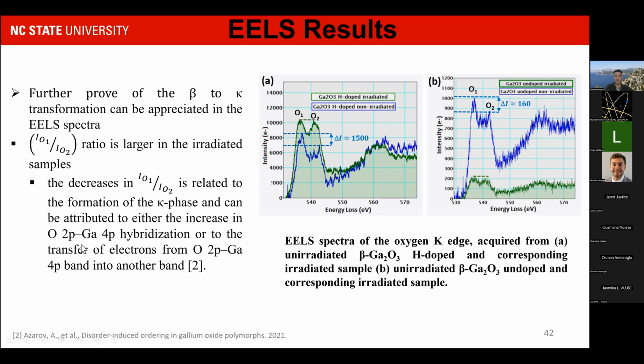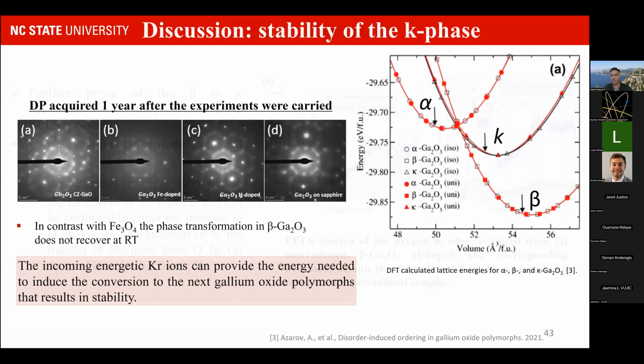It can be attributed to either the increase of the O2, the oxygen that have a specific position in the monoclinic structure, or to the transfer of electrons from O2 to the 4p band into another band. So we observed this type of information consistently throughout, regardless of the sample and regardless of whether it's doped or not. Interestingly, the stability is not just under irradiation by further irradiating, but also over time. So I had my student look at the same samples 1 year after the experiments were done, and the diffraction pattern showed that the kappa phase is very stable even after a long time.